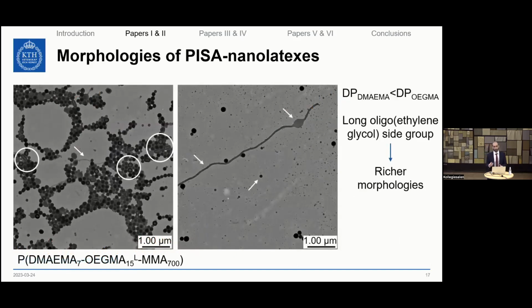We found out that when the macro-RAFT agent that we used was comprised of more OEGMA than DMAEMA, and when the length of the oligoethylene glycol side group was the longest, then we have rich morphologies. We can have the coexistence of spheres, worms, and even vesicles at different time intervals of the polymerization. We realized also that when we increase the pH of the dispersion, and we go closer to the pKa of PDMAEMA, which is approximately 7.8, then these nanolatex dispersions, even though in some cases they retain their morphologies, they either aggregate or precipitate in some extreme cases. So this is something that we need to look further into in the future.